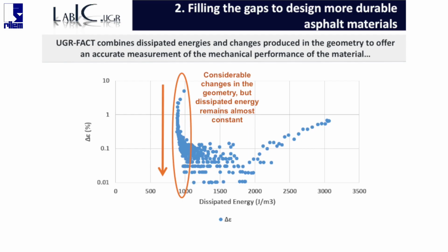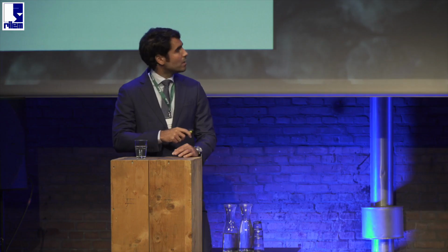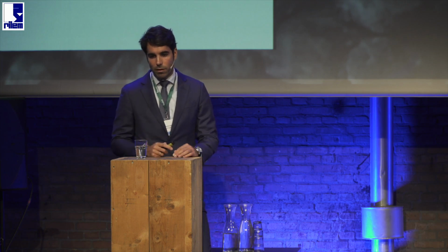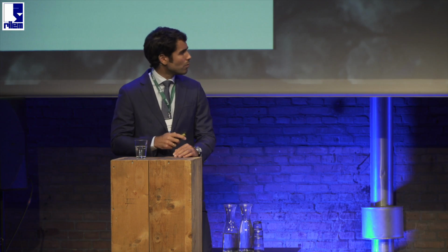So basically, at the beginning of the test, in all tests, we can observe a considerable change in the geometry of the material. Consider that this is a logarithmic scale, so we are going through a considerable change in the geometry of the material, but the dissipated energy remains almost constant. So that means that there's no damage in my material, and the deformation that we are controlling is only due to plastic deformation or other viscoelastic phenomena such as heating or other.